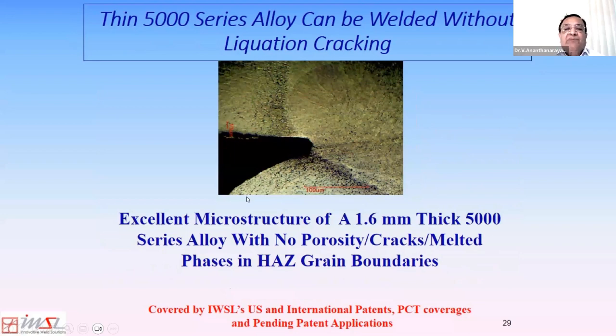The separation between the weld interface here is due to peel testing. The lower side was pulled apart in an effort to do a peel test. And in the peel test, obviously, in this case, the materials did not come apart. And you can see that cooling of the heat affected zone helps you counter liquation cracking as well.